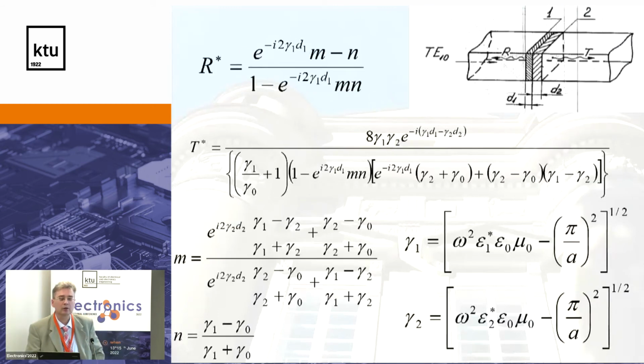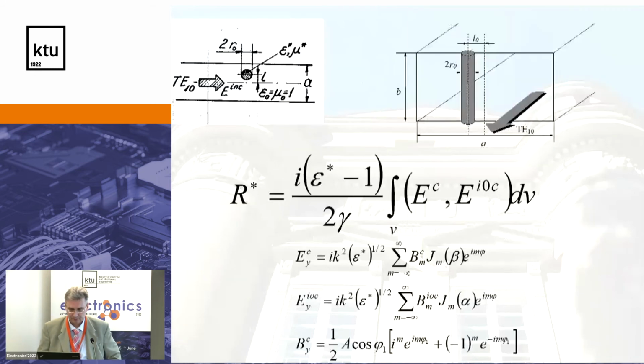Also, full cross-section filling is possible to calculate the thin film's properties. If you place substrate, thin film, and you know substrate dielectric properties, you can extract from reflection and transmission the properties of the film. But as I mentioned, for PZT or barium titanate at gigahertz, its reflection will be 1.